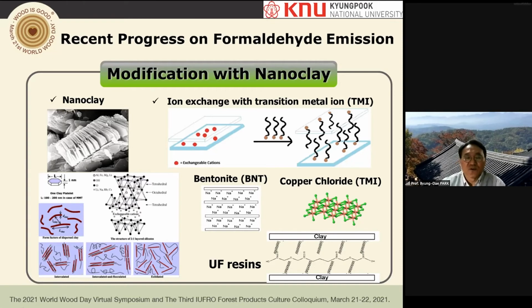So the idea is that we want to exchange the sodium ion with a different, bigger ion, which means copper chloride. We have the sodium cation here, and we exchange it with copper ions because the copper radius is much bigger than sodium. Then what we expected is a larger distance between the nanoclay layers, and that the UF resin molecules would sit between the nanoclay layers.